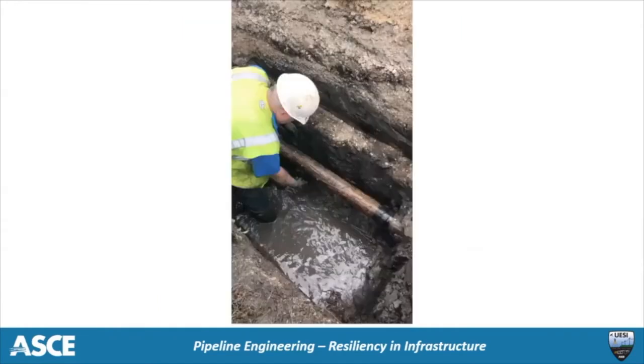Paul Hansen, one of our regional directors, is removing the film from the pipe. You can see we've wrapped tape around both ends of the exposed pipe in order to facilitate the removal of the film and also to facilitate the replacement of the film after the investigation has been completed.